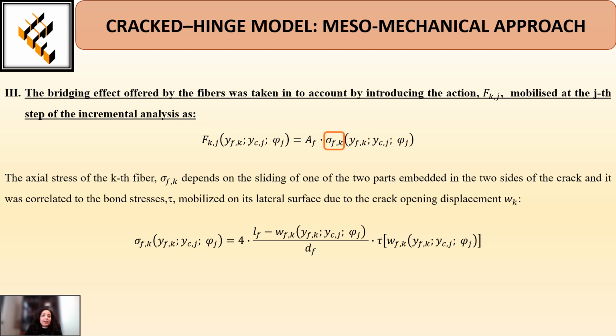In the end, as regards the fibers, the bridging effect offered by the fibers was taken into account by introducing the action Fk mobilized at the jth step of the incremental analysis as the product between the fiber's area and the axial stress that depends on the sliding of the two parts embedded in the two sides of the crack, and it was correlated to the bond stresses but also to the crack opening displacement.